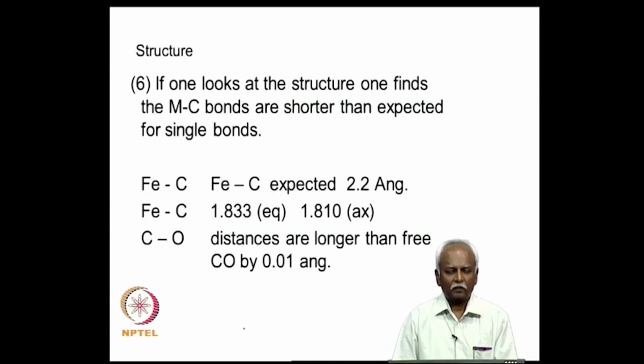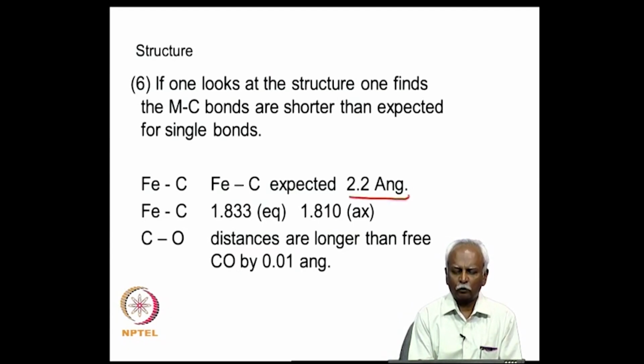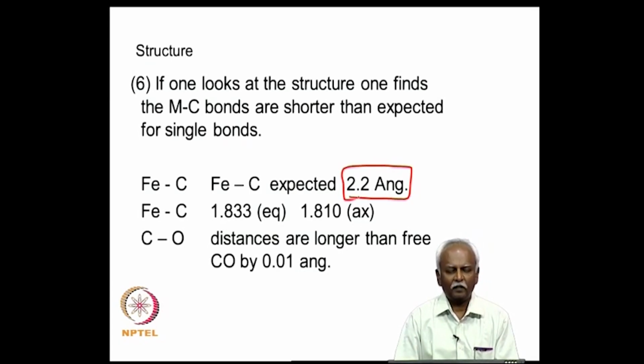Let us now move on to the structure of these compounds. We find that the structure of these compounds is governed by this 18 electron rule, but more than that, they are not single iron metal carbon bonds. If you take the typical example of Fe(CO)5, the iron carbon bond that you would expect on the basis of the covalent radius of iron and the covalent single bond radius of carbon, if you add these two together, would be a bond distance of 2.2 angstroms. So, 2.2 angstroms is what you would expect on the basis of adding the two single bond radii of the two elements, iron and carbon.